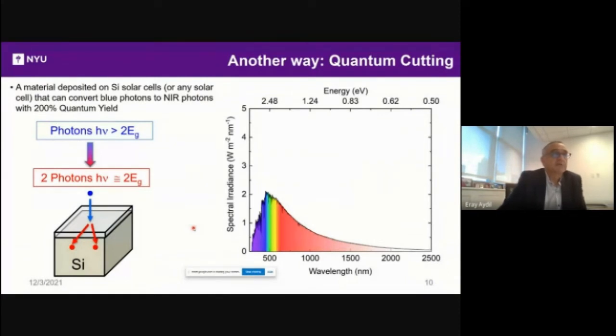So this whole problem is arising because the solar spectrum is not well matched to the silicon's band gap, okay? Silicon's band gap is around 1100 nanometers here, whereas as you can see, there's a lot of high energy photons in the solar spectrum. It would be nice if we took these blue photons and made 2 photons of lower energy. This 2 is a typo. It should be 1 band gap. So we take twice the band gap energy in the blue, and we make 2 photons of 1 band gap energy, which is depicted here with the schematic.